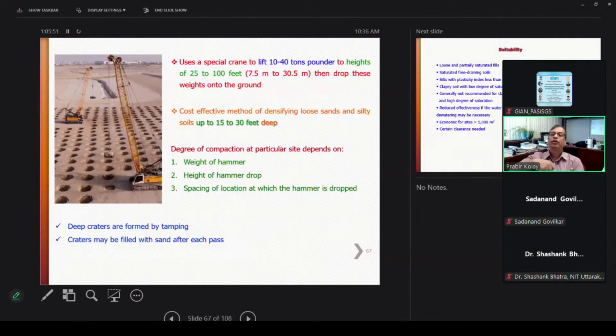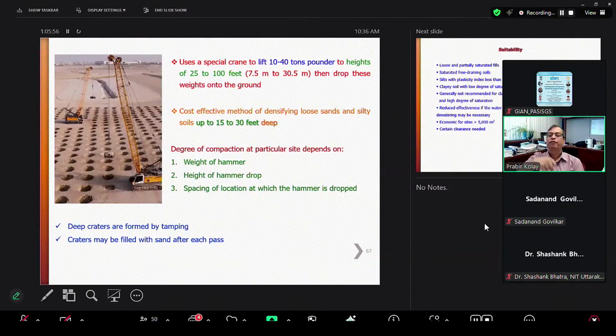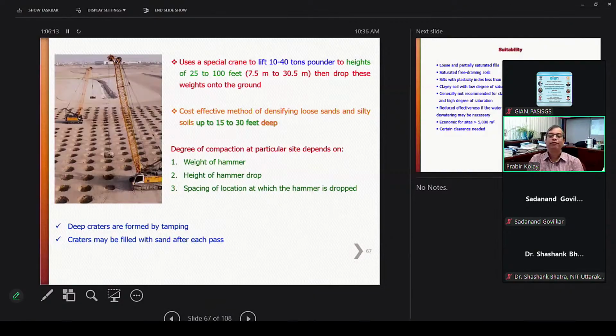Basically, a huge crane is required to lift a 10 to 40 ton pounder to a height around 25 to 100 feet, and then drop this weight onto the ground. It is a cost-effective method to densify loose sand and silty soil up to 15 to 30 feet deep. So if you want to improve the strength of the sand 15 to 30 feet deep, this is a good method. You just drop it.